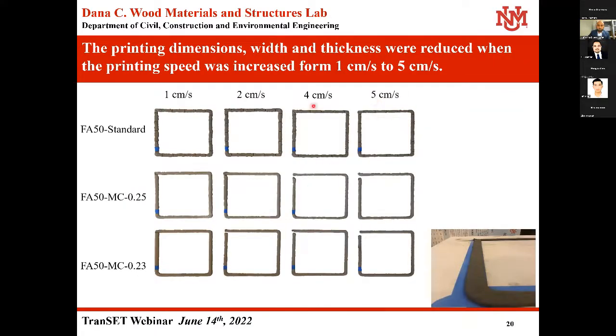We also investigated the effect of printing speed over the printing quality. When printing speed was increased from 1 centimeter per second to 5 centimeter per second, we observed a reduction in filament dimension, that is thickness and width, from 1 centimeter per second to 5 centimeter per second printing speed.